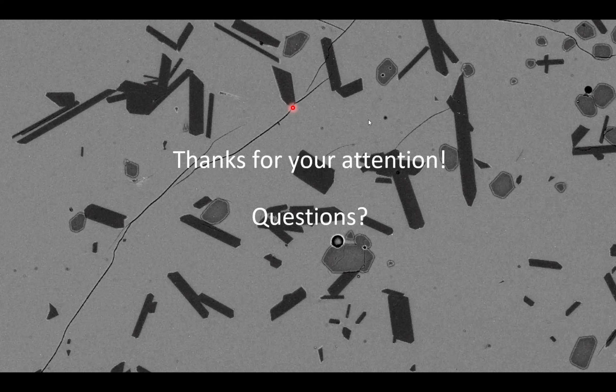Well, I did not use them for these experiments, because they were all done, what I showed you, in the argon-only vessels, where we only use the argon as a pressure medium. So we have no direct control on the oxygen fugacity. It is directly controlled just by the argon itself, which we then constrained with another study where we measured the intrinsic fO2 at more or less similar run conditions to be at NNO plus 2.3. It was the same vessel which I used, so I assume it should be the same. All these sensors you saw were done over, I think, a period of one year, so we did not observe any alteration or change of the vessel buffering capabilities.